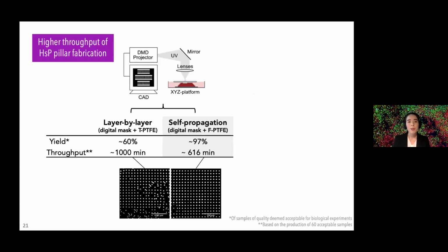The single step process also significantly improved the throughput, or the fabrication speed, circumventing the time costs associated with stepwise vertical translation of the platform. This simplicity and uniformity of the vertically oriented artificial axons accomplished with a single exposure motivated us then to pursue more simplified fabrication methods, which could be amenable to large area fabrication to generate a large number of samples in less time for things like high throughput drug screening, where you typically require multi-well plates full of these structures.